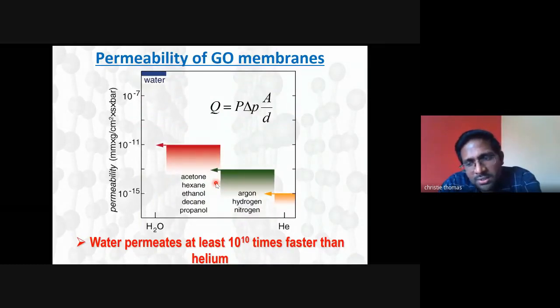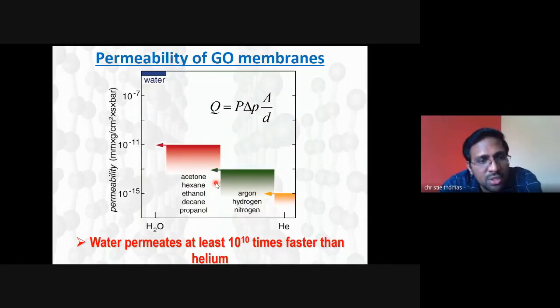Okay, what is the speciality of this graphene oxide membrane? You can see here, water goes through. If you take a micrometer thick graphene oxide membrane, water goes very fast, orders of magnitude faster than organic solvents or other gas molecules.